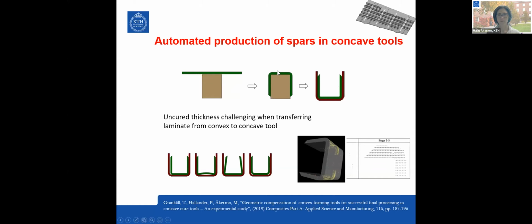If you design this convex tool precisely the size that you have here, then you will get into troubles when you try to force it into the geometry. And as soon as the material softens up and you debulk the material, you will lose the pressure. So what we did in this study was try to look at different approaches where we required some material sliding from up to down to cover the lower sides.